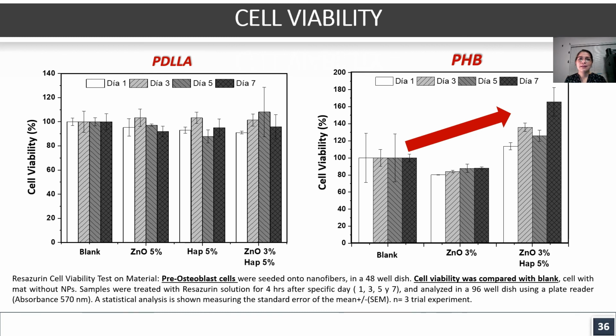Given that hydroxyapatite in the binary system did not show a significant impact on cell behavior, and taking into account the screening effect of hydroxyapatite observed in the antimicrobial study of the ternary system, it could be inferred that the combination of nanoparticles is exerting a synergistic effect that promotes an increase in cellular performance, which is more pronounced by day 7.